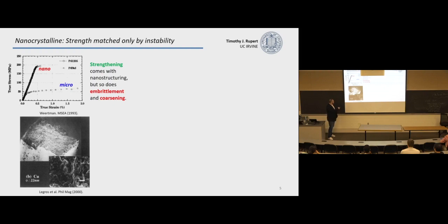And you can see evidence of that when you look at fracture surfaces. So typically when we pull on a metal, we get this long cup and cone failure where you can see the material stretching like Play-Doh at the surface. In this case, in some of the early nanocrystalline copper, they were seeing these very brittle fracture type of surfaces.